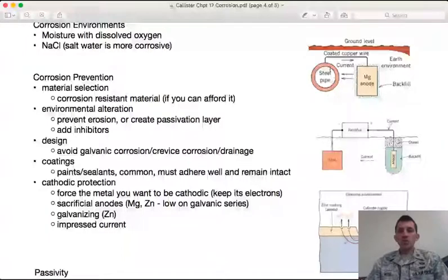And to protect it from corroding, because it's going to be in contact with groundwater and a corrosive environment, you can provide a current path, say through this copper wire, to a chunk of magnesium. Ions can migrate through the groundwater in the soil, and I have changed the nature of the corrosion reaction.